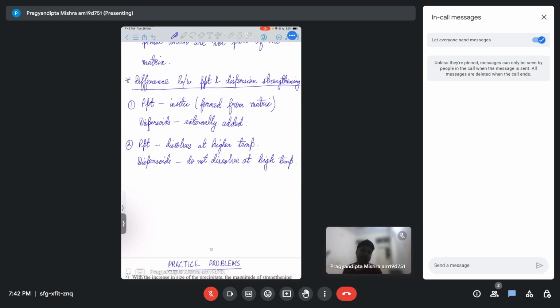Okay. So essentially, dispersoids will also act like precipitates, but dispersoids have one extra condition added on, which is that they do not dissolve at high temperature. So for high temperature applications, instead of using precipitates, you can use dispersoids. Okay, but mind you that dispersion strengthening is actually much more difficult than precipitate strengthening, which is why people prefer precipitate strengthening, because it is much easier for us to form precipitates than dispersoids. Okay.